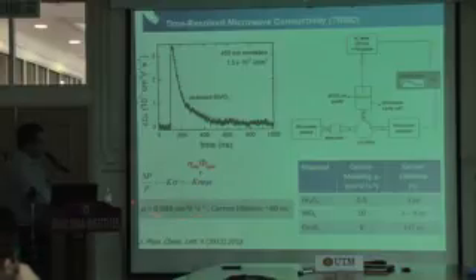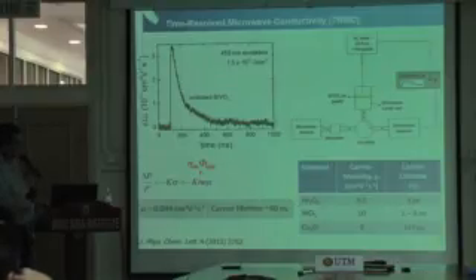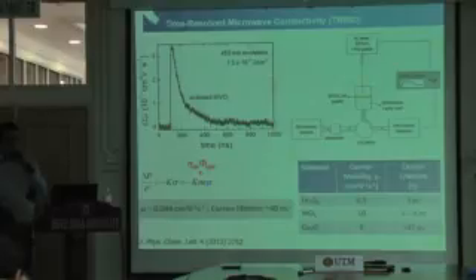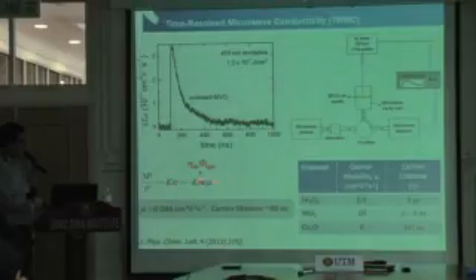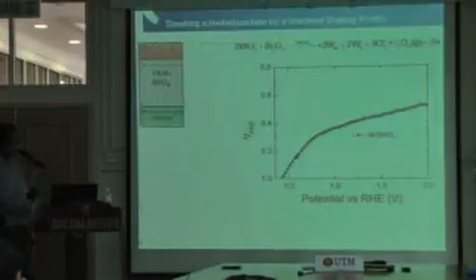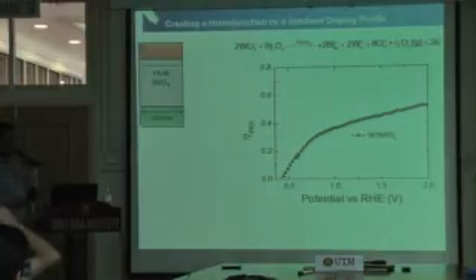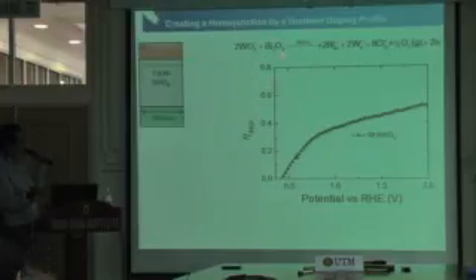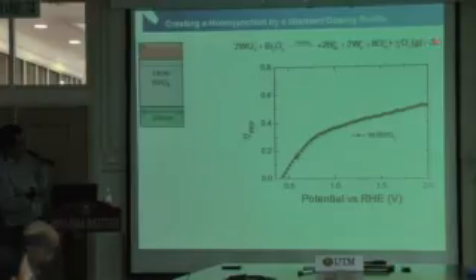So this mobility is then a problem that we have to solve, right? So this is maybe the reason for poor charge separation. But if we take a look at the conductivity again, modifying mobility is actually much harder than modifying carrier concentration, right? Since conductivity is a product of these two, we chose to play around with the carrier concentration, and we do that by doping. So we dope our bismuth vanadate with tungsten, co-doped with bismuth actually, according to this defect chemical equation. If you take tungsten here to replace vanadium, and you do it properly, you can get compensated with the additional 2 electrons over here.